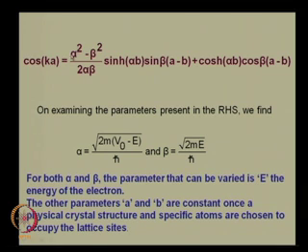What we will find is, based on the energy values you choose, this entire expression here will on several occasions fall within the plus or minus 1 window, and on some occasions this expression on the right hand side will evaluate to values which are greater than this plus or minus 1 window. So you may have, for example, this expression evaluate to a value of 1.2 or 1.5 or some such thing for specific values of energy. That therefore gives us a situation where this becomes an absurd, or an inconsistent, relationship.